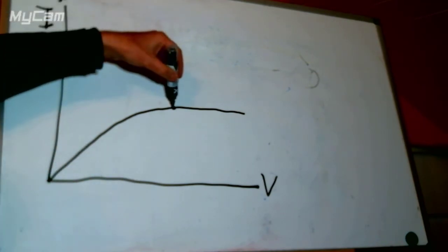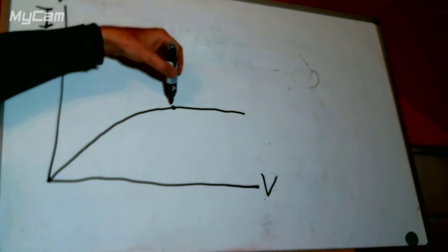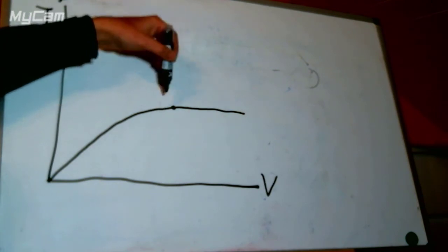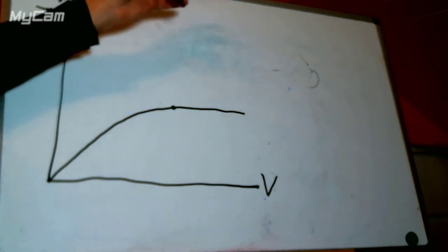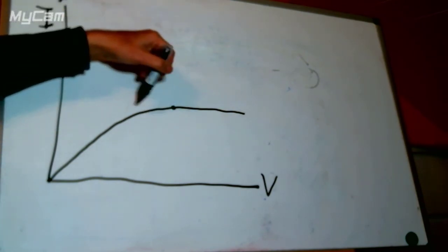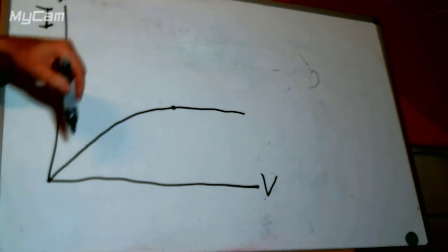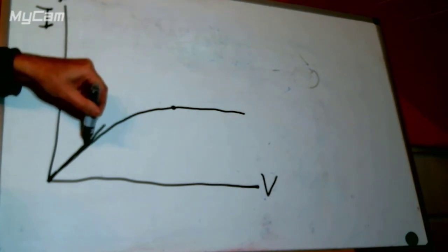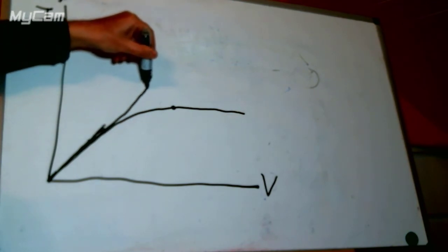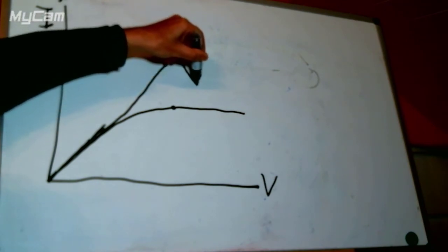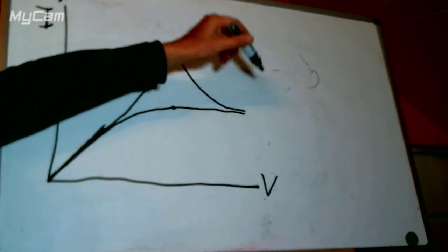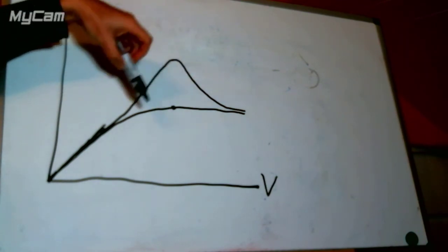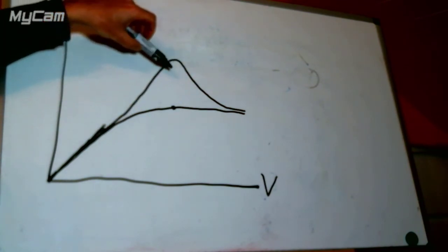At this point, if we go infinitely slowly, we've got copper in solution already, and so it's just diffusing away at the speed it's diffusing away. But if we get there quicker, there's not any in there, so we've got more space for it to go into. So we would expect to see a current similar to this, but it will go up past, and then it will come down to this value. It goes past because there is no copper in solution close by. If we go fast enough, there's none at all.